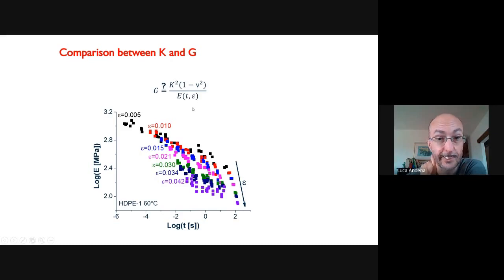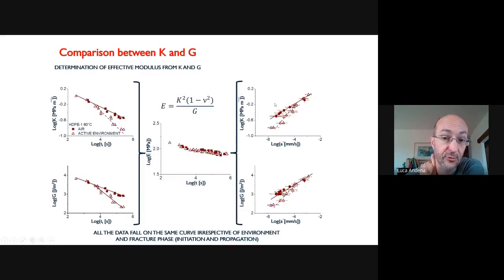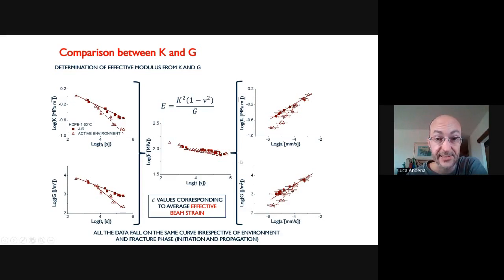So can we still try to make a comparison between G and K data? Short answer is yes, provided we take strain correctly into account. To demonstrate that, I have a slide in which we basically took G data and K data and used them to determine an effective modulus, which is based on this equation. And not only do all the data points fall on a single curve, but what you can also check is that the curve of modulus versus time that you obtain is related to the value of the strain that you would expect for a sample bent like the fracture samples you are testing. So the answer is yes, it works.